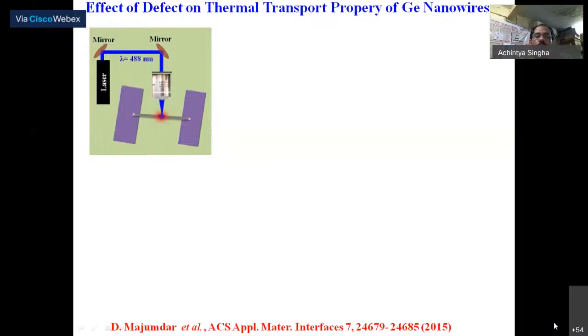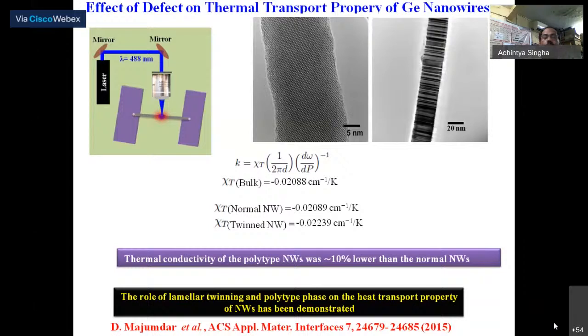So we used two types of nanowire, as you can see in the same picture. One is defect free; this is a very clean sample. Another is a defective sample. We wanted to compare their thermal conductivity using the same method. And we found that the thermal conductivity of the defective nanowire is 10% lower than the defect free nanowire, because the defect sites give some extra scattering that restricts the thermal properties of this material. So using a very simple experiment, you can get the thermal properties of the material. Go next.